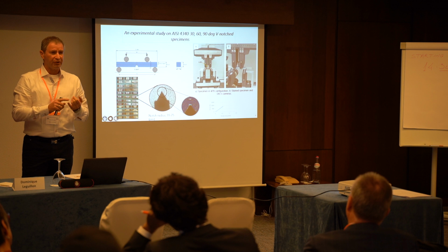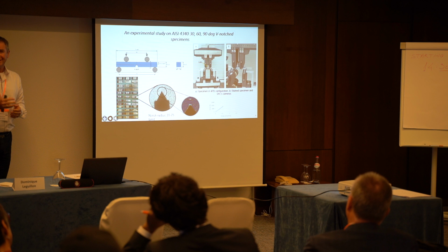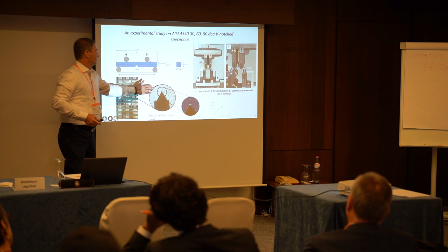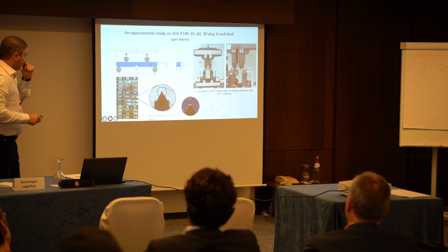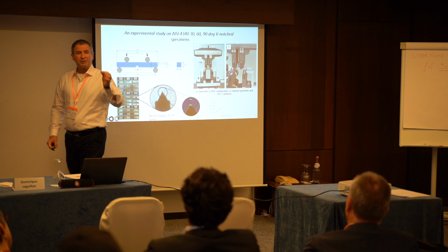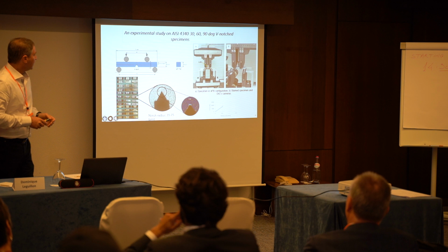And I'm very glad that we had a discussion about the DIC before, because we did the DIC very close to that notch tip, and we wanted to find out what is the plastic zone which is being generated when we load the specimens. And we did these experiments, and you can see very clearly here that we have a linear response almost until fracture, and we were very happy that this is what happens. So we did all these experiments, and then we applied the criterion.